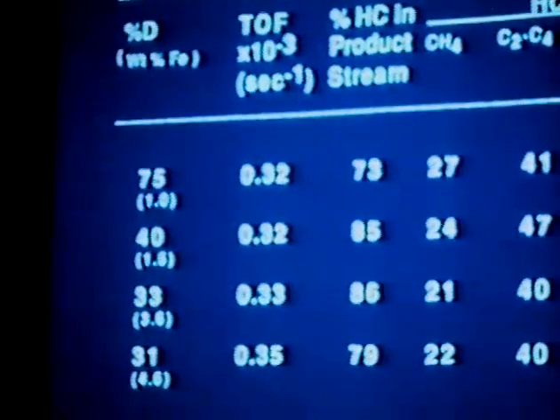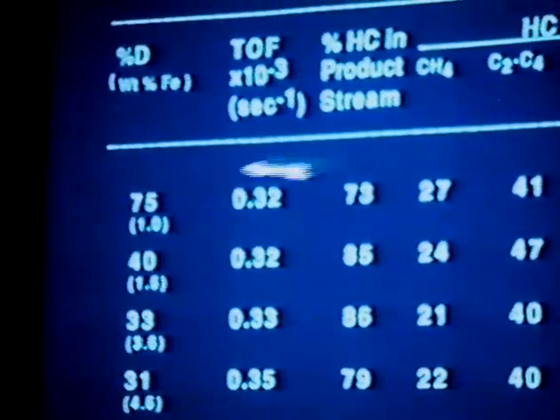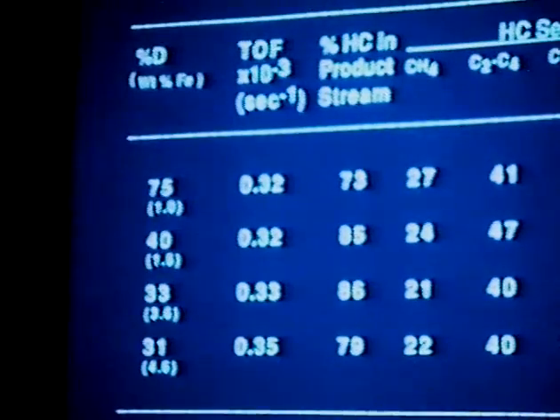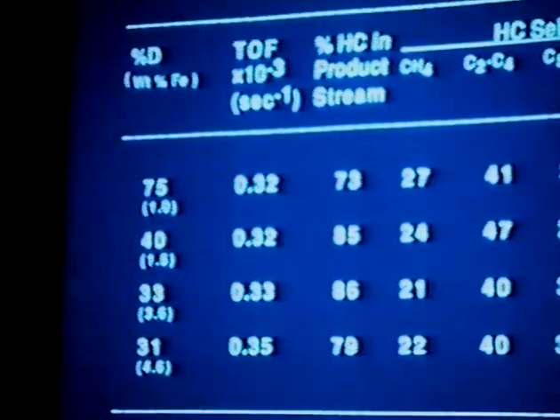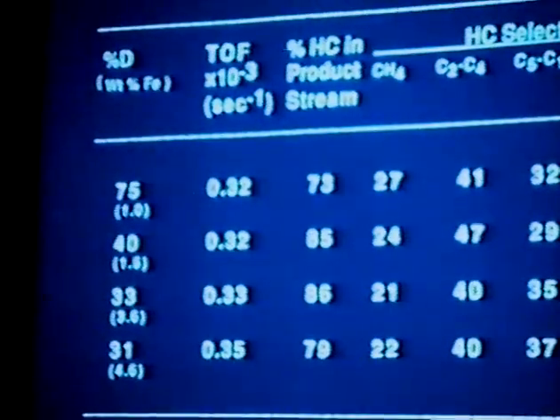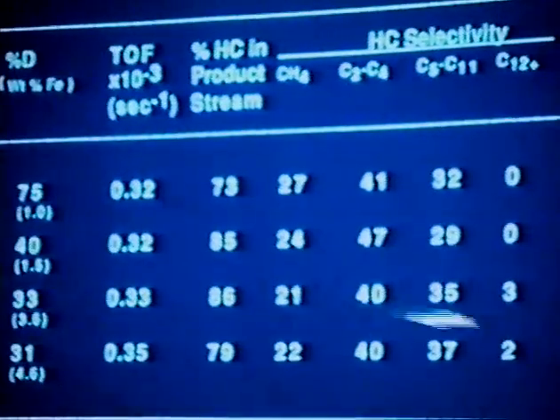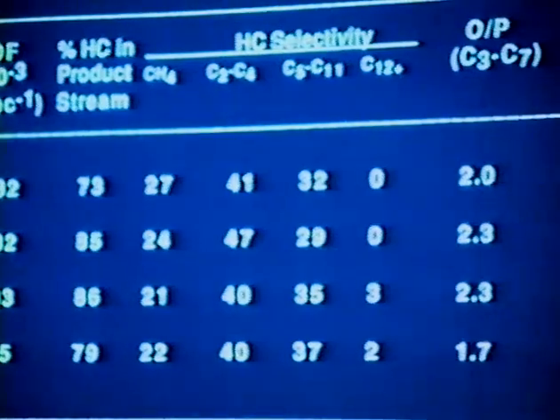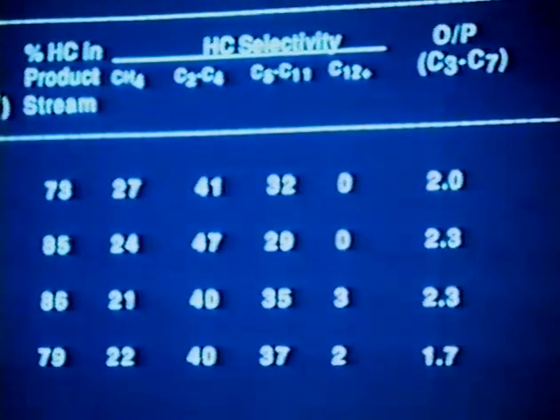Now let's look at the activity and selectivity data for these catalysts. As the dispersion increased while holding the extent of reduction fairly constant, the turnover frequency remained almost the same. And the hydrocarbon selectivity also remained the same. And if you look at the individual product selectivity, this too remained fairly constant.